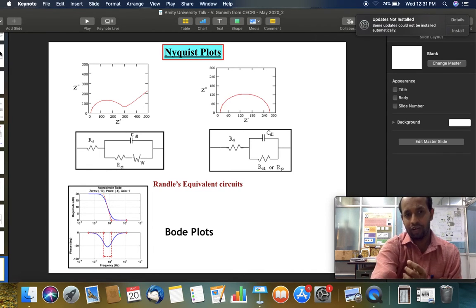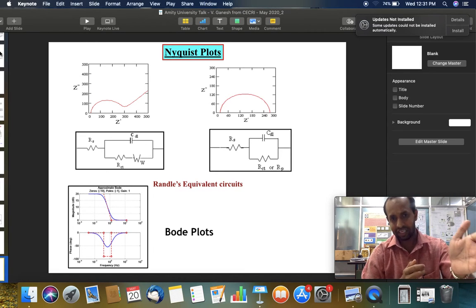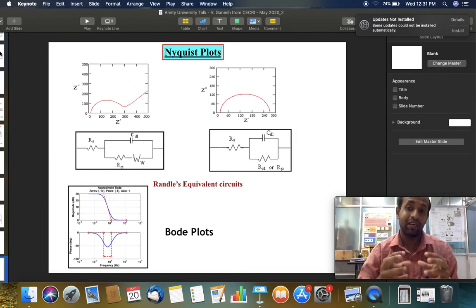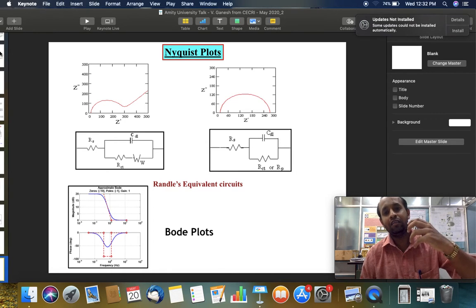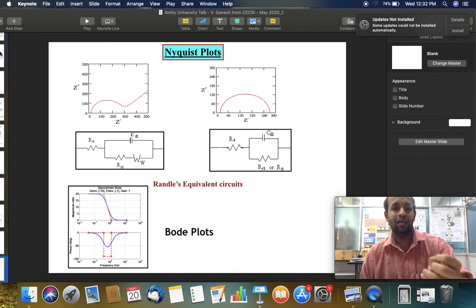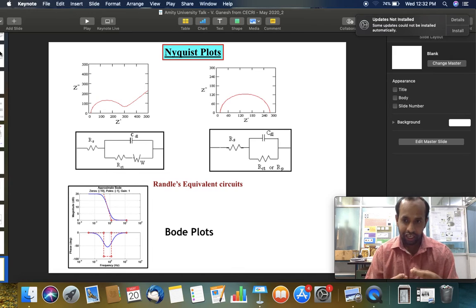Okay, on the other hand, if you observe a small semicircle and a straight line, like the one on the left side of the slide, that tells me that the given electron transfer process is controlled by diffusion. The formation of the semicircle is due to charge transfer control, and the formation of the straight line is due to a diffusion controlled process. Okay, so thanks to the parallel development in electronics, we are able to understand the interface much better by fitting the impedance output to a suitable equivalent circuit, so that you can measure quantified parameters of double layer capacitance, charge transfer resistance, which in terms of corrosion they name polarization resistance, and Warburg, which is W, that describes the diffusion component.